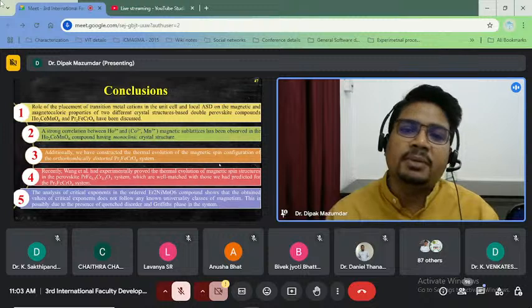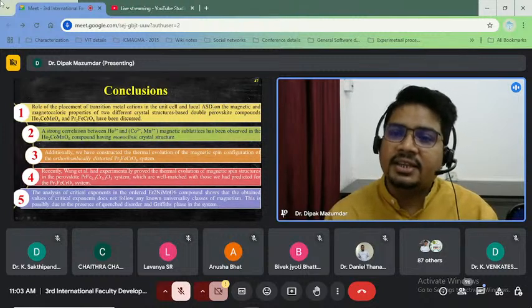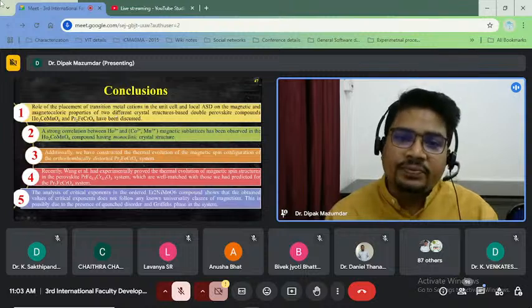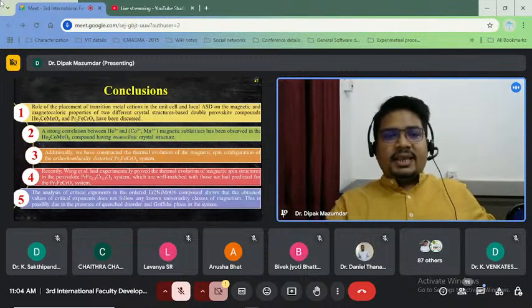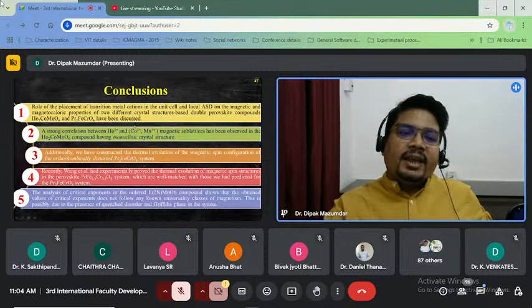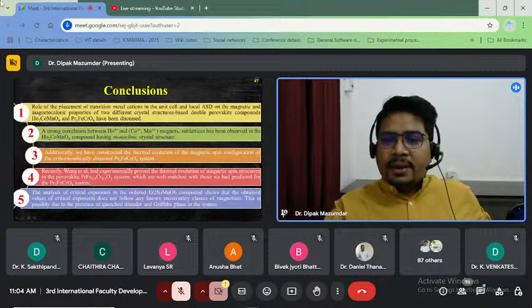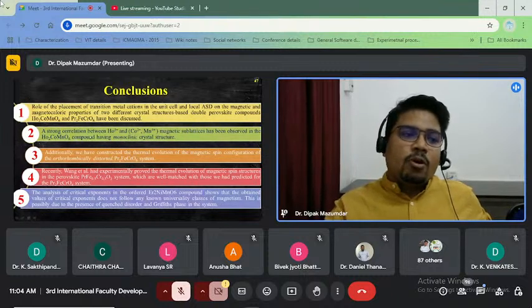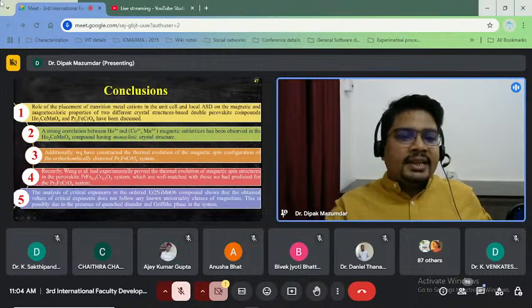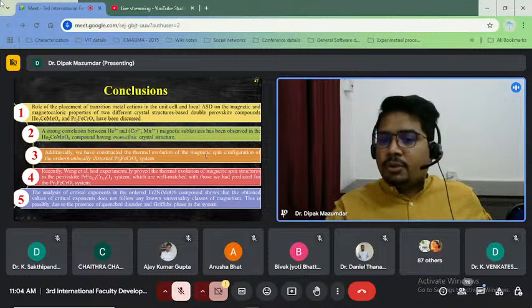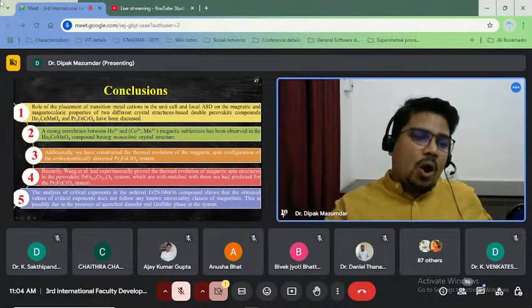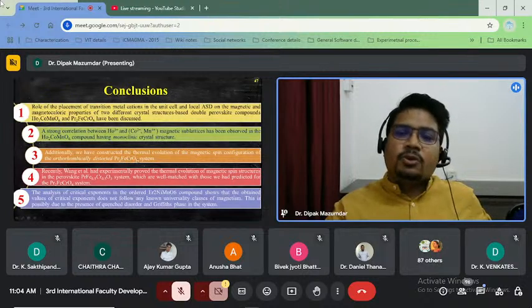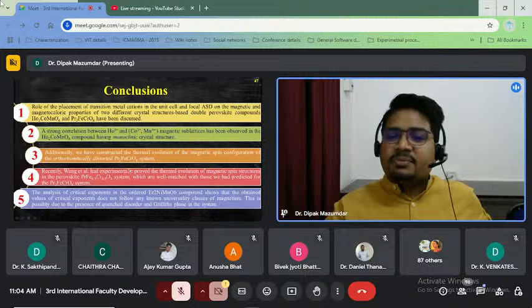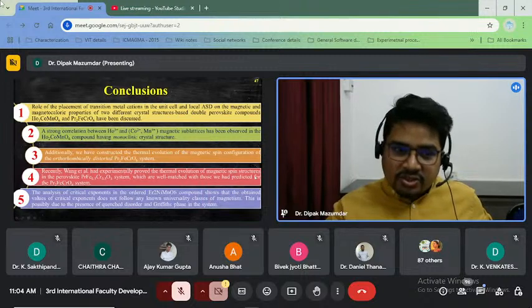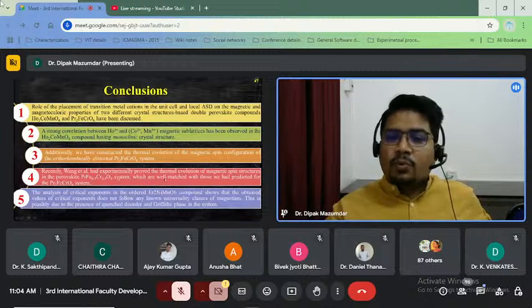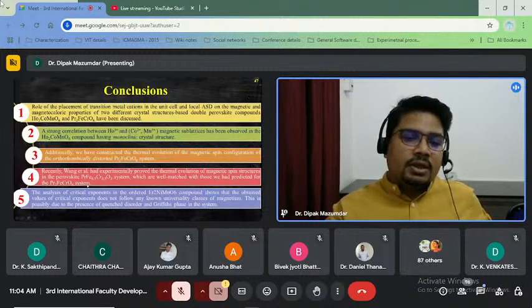The role of placement of transition metal cations in the unit cell and local ASD on the magnetic and magnetocaloric properties of two different crystal structure-based double perovskite compounds, HCMO and PFCO, have been discussed. A strong correlation between holmium and these transition metal magnetic sublattices has been observed in the HCMO compound having monoclinic crystal structure. Additionally, we have constructed the thermal evolution of the magnetic spin configuration of the orthorhombically distorted Pr2FeCrO6 system. Recently, Wang et al. experimentally proved the thermal evolution of magnetic spin structures in the perovskite system, which well matched with those we had predicted for the Pr2FeCrO6 system.